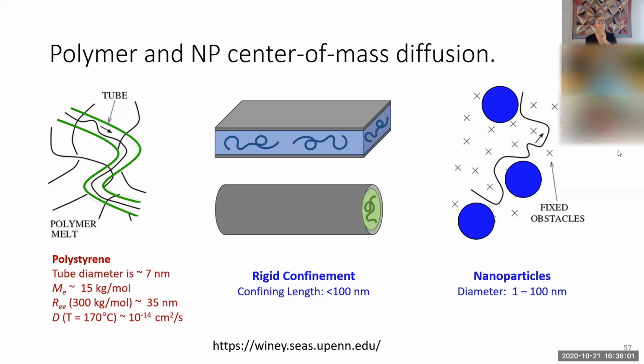Right. So we've done some segmental dynamics as well. P2VP and silica has also been studied a lot by Alexei Sokolov's group. Right at the nanoparticle, that strong interaction does slow down segmental dynamics, and you can see that in electrical impedance spectroscopy. You can also see it in a higher Tg. Once you have enough particles there, you've slowed the segmental dynamics of enough segments that you can pick it up in DSC, even modulated DSC. And we just published a paper using quasi-elastic neutron scattering, where we had two different P2VPs, where in one the whole chain was deuterated, and in the other only the ring was deuterated. And the slowing down happens in both the ring and the backbone. So it turned out not to be that interesting.